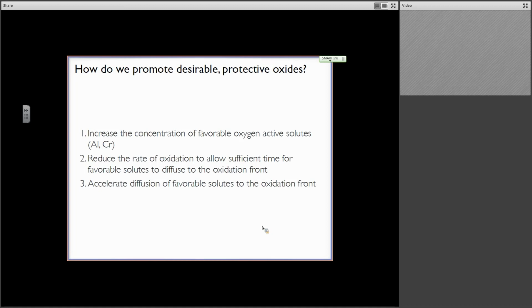And aluminum is a little bit more finicky though. But the consequence of adding these solutes is not only that you increase the cost of the alloy, but you also may change other properties like the mechanical properties. Adding aluminum in excess to many iron and nickel-based alloys actually significantly reduces the strength. So we have to be very careful about this particular strategy.